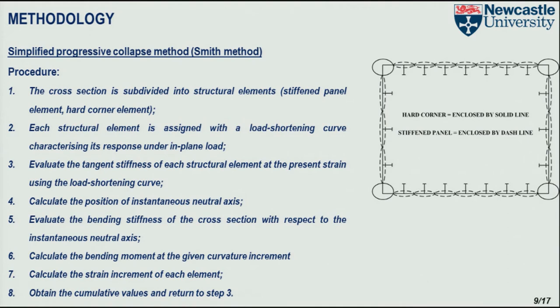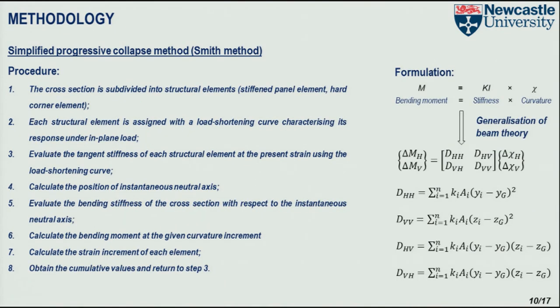As I mentioned, I will also do some finite element analysis to validate the simplified calculations. These are some of the finite element modeling techniques we usually adopt. To predict the ultimate strength of a ship hull using finite element, we normally don't need a full ship model because it's almost impossible to complete the analysis. Instead, we will take a slice of the midship, and in our case, in hull girder strength assessment, that should be enough. We develop a 9-bay midship cross section using four-node shell elements. The element size is roughly 100 millimeters by 100 millimeters.